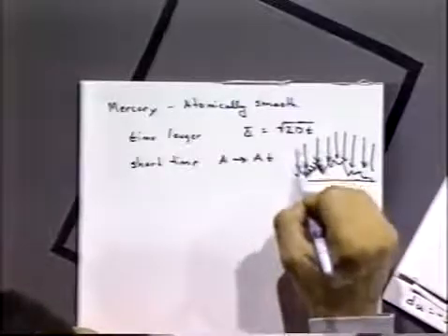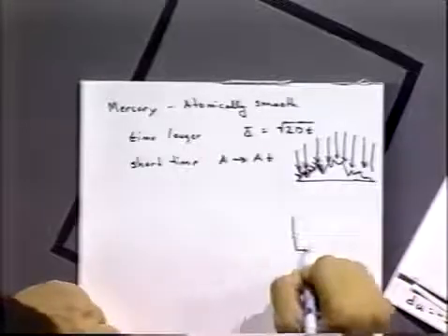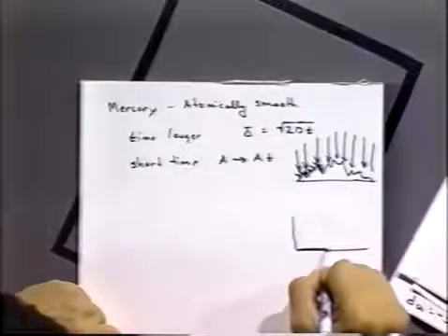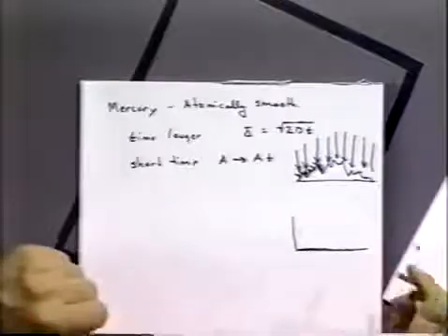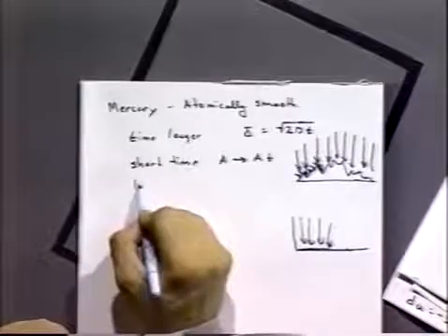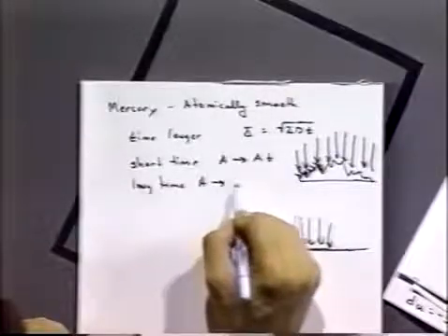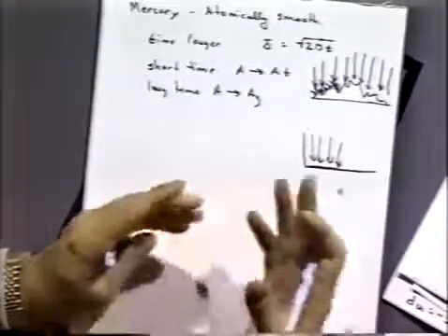All those little ridges and bumps sort of get smoothed out. And so effectively at long time scales, our electrode is maybe just rough on that sort of time scale, and it really hardly makes any difference. So at long times, A would approach the geometric area. And so you could actually do this measurement by doing a Cottrell experiment.